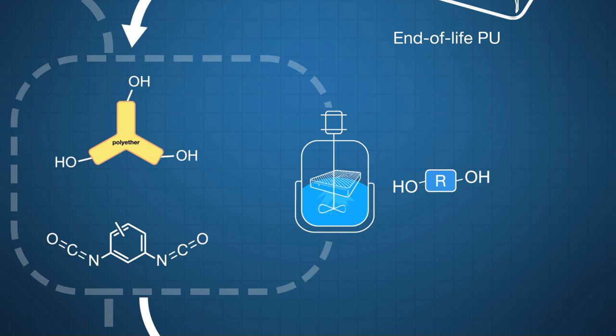This comprises the dissolution and depolymerisation in a polyfunctional alcohol in the presence of a catalyst at around 200 degrees Celsius.